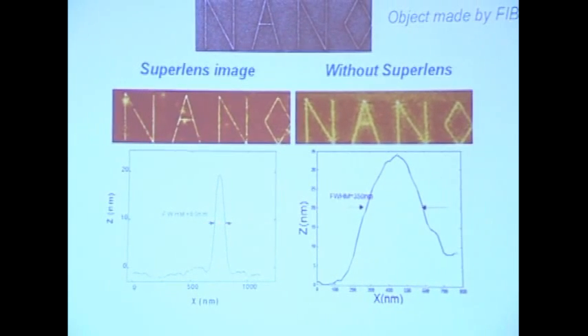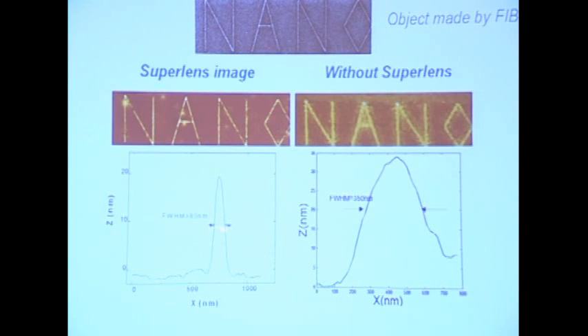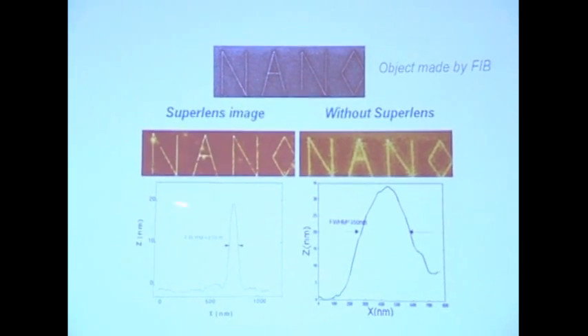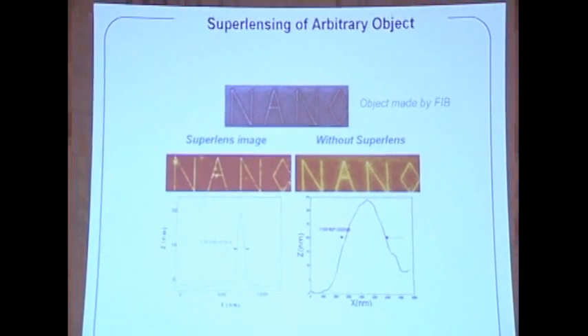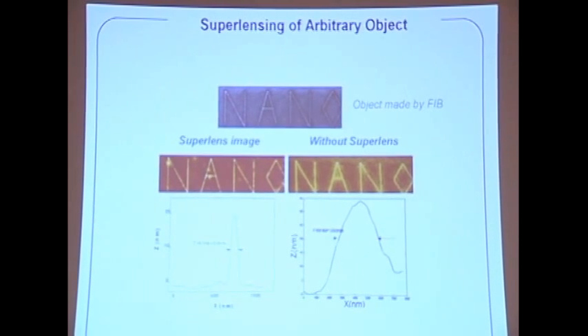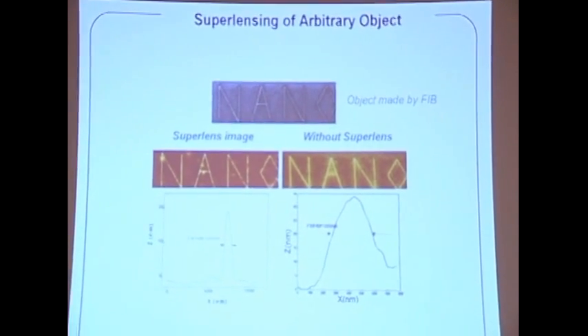However, with the superlens, you will be able to see way below the diffraction limit, about 80 to 90 nanometers. So that shows that indeed this is imaging below the diffraction limit. So this is a nice demonstration of the physics of superlensing.